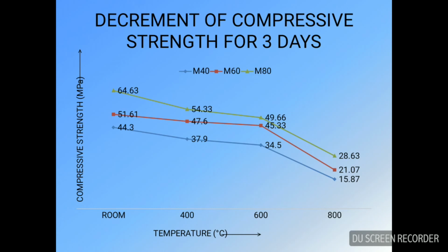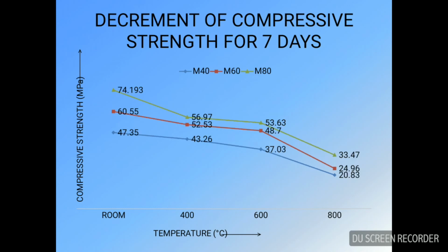As you can see, there is no major decrement up to 600 degrees Celsius, but from 600 to 800 degrees Celsius there is a major downward curve, which shows that above 600 degrees Celsius the rate of degradation increases, and at which rate it is degraded has been discussed in the conclusion. Similarly, the decrement of compressive strength after 7 days also had a major drawback, with the strength decreasing from 600 to 800, a downward curve.